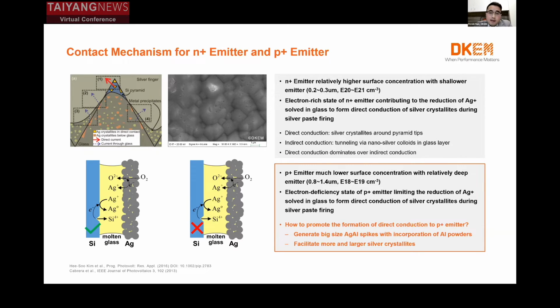It's quite different. And the other one is that the p-type surface is lean of electrons, so it's not good for the reduction of silver ions dissolved in the glass system to form the silver crystallites during silver paste firing. The silver crystallites play the role of direct conduction. It plays a dominant role for the contact formation. So the issue is how can we promote the formation of direct conduction for p-type emitter? That means a lot to the success of TOPCon solar cells.